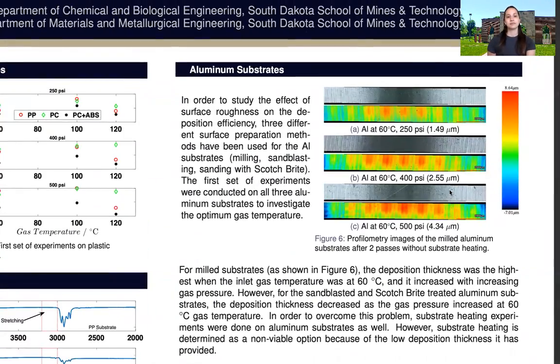With the aluminum substrates, we used 6061 composition with 3 different surface roughnesses. We prepared different surfaces with milling, sandblasting, and Scotch-Brite treatment. Then we conducted the same first set of experiments to determine the optimum temperature. For the milled samples, the deposition thickness was the highest when the gas temperature was at the lowest end, 60 degrees C, increasing with increasing pressure.